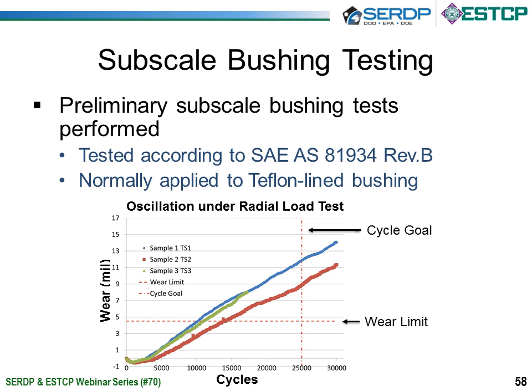the bushings actually showed very linear wear. There was no obvious damage to them. There was no distress on the wear surfaces. And the testers also observed a very low sound generation for these materials, given they were tested in the unlined form. So although it's not an ideal test, and we will conduct future tests on these materials, the results were overall encouraging, and I think they certainly merit future work.